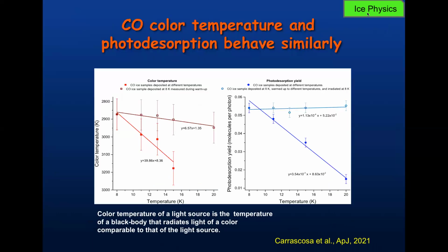We compare here the color temperature of the ice with the photodesorption yield, and you see that if you warm it up, it doesn't change much in both cases, but if you grow it at different temperatures, it follows a similar behavior. So it means that photodesorption is sensitive to this ordering of the ice.